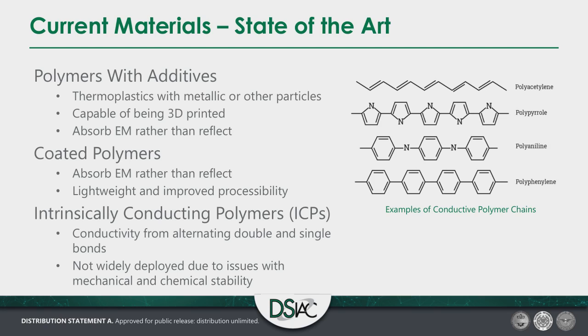Other available materials include polymers with additives — the sky can be the limit. Thermoplastics can act as a carrier vehicle for any number of additives: carbon fiber, metallic nanoparticles, and more. You're limited only by what you can mold and solidify into a part. Coated polymers absorb EM rather than reflect it — they're lightweight with improved processability. Intrinsically conducting polymers are another option: unlike normal plastic, some polymers are conductive through alternating double and single conjugated bonds, allowing mobility of electrons and mobile charge carriers. However, these are not widely deployed due to issues with mechanical and chemical stability.